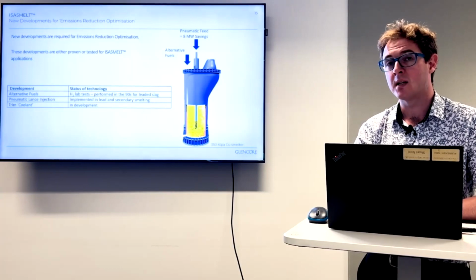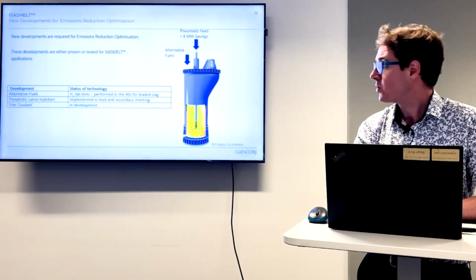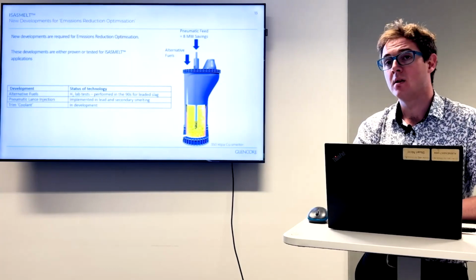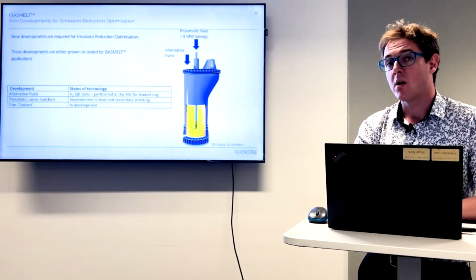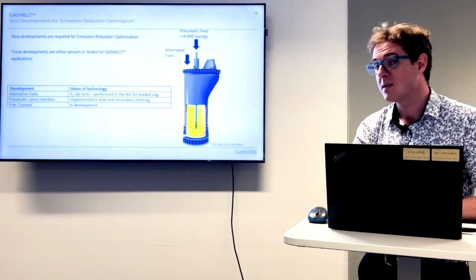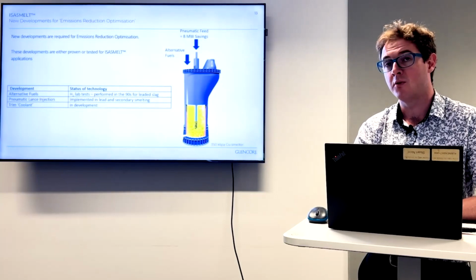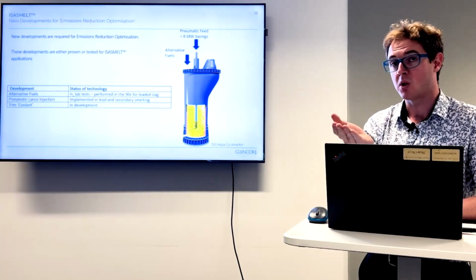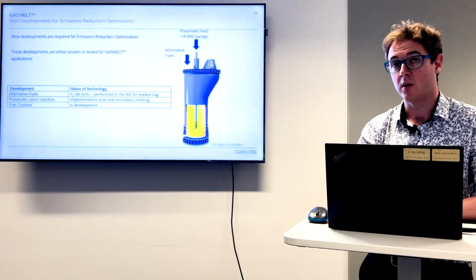We've also got short-acting trim control. This goes down the lance and acts instantly in the furnace, so this gives us instantaneous temperature control. Traditionally we've used fuels down the center of the lance, things like natural gas, diesel, and other liquid fuels. If we're going to go to net zero, we're going to have to move away from these fuels as our trim. Instead, we have to move to a coolant. So this means we're going to shift the energy balance of the furnace slightly. Currently these furnaces are designed to be slightly energy negative, and that trim fuel adds enough energy to get it smelting at the temperature we want. If we run at energy positive, rather than using a fuel down the lance, we can use a coolant.